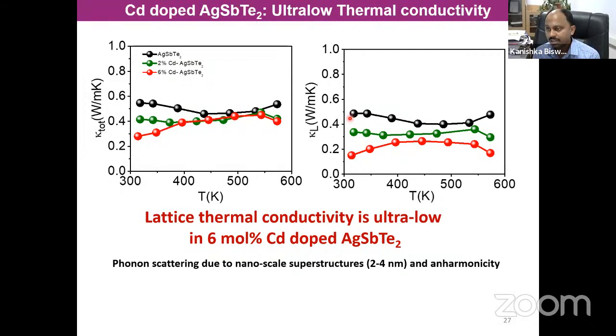It's around a few nanometers only, and that gives actually a glass-like transport, which is well known. But it decreases more as soon as I dope cadmium, because it has these nanoscale domains which have a huge amount of phonon scattering and give rise to this ultra low thermal conductivity, which is at the glass limit of this material, 0.2 watt per meter Kelvin.